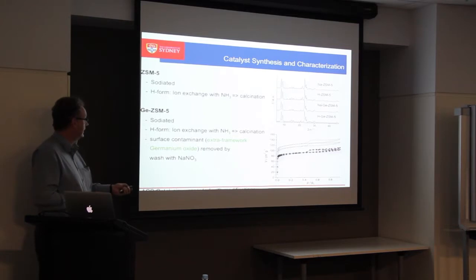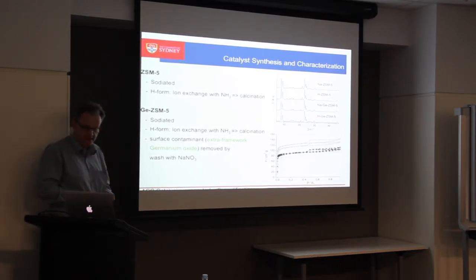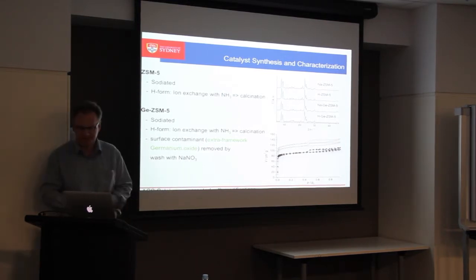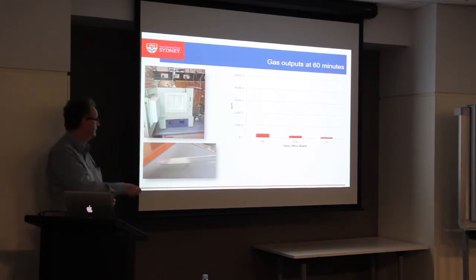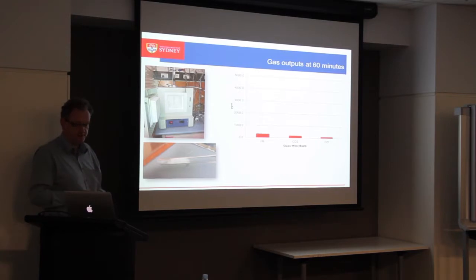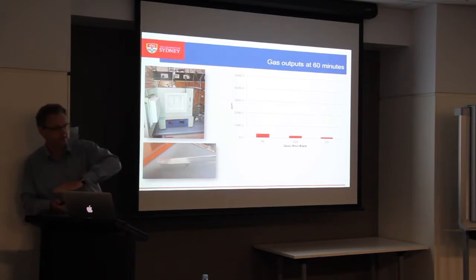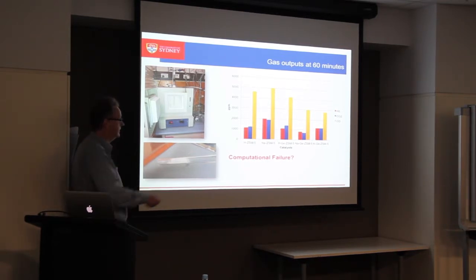There is a literature method to remove the extra-framework germanium oxide just by washing with sodium nitrate — what could be easier? We've got the appropriate pore volumes and surface areas. Now we look at our blank reaction. This is our reactor, glass wall. We know glass wall is a little bit active for this, so we've got to take that into account. Here's our tube reactor — gases go through. This is our background reaction.